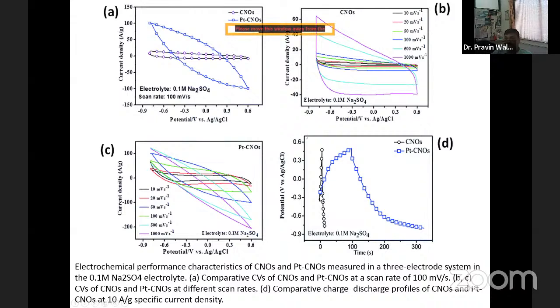But the moment you decorate the platinum on that, you can see this is increasing. So the charging time is also increasing and the discharging time is also increasing. It means, if there is a large charge stored in your material, it requires longer time to discharge. And if there is a large capacity to store the charge, it will require more time to charge.